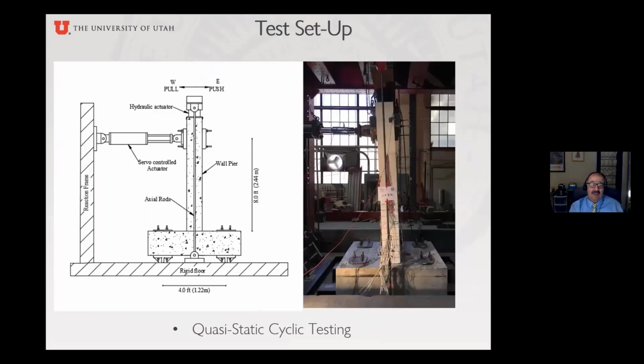So the way we test this, we apply an axial load, about 6% of the capacity of the wall. That's typical. And then we apply a lateral load at increasing drift ratios, as you can see here with this actuator. And that's how we keep track of how far the wall is moving in an earthquake. Here you can see it, for example, when it's moved about 5%. 5% of 8 feet is about 5 inches. So when it's pulled back 5 inches, you can see how it looks. And then this axial load is applied with the rods reacting against the beam from a hydraulic actuator.